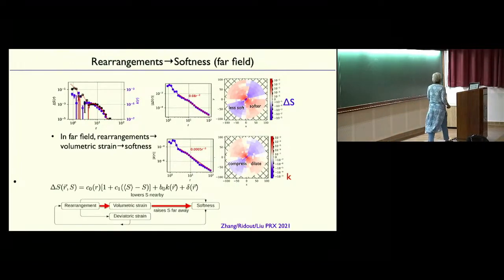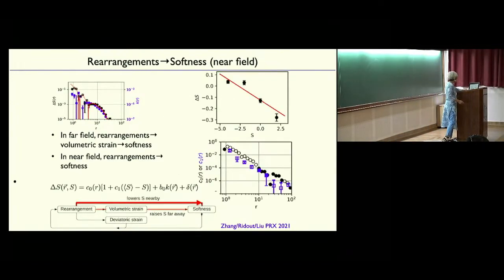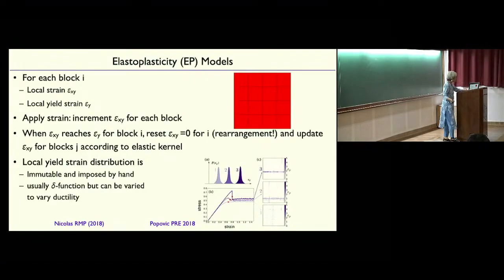That's the near field effect. And it turns out that the near field effect has a different form. You can subtract off the far field effect and look at what's left. And what you see is that the near field effect has this simple form where I have a coefficient that decays with distance, okay? And then there's something that wants to drag softness to its average value. So what happens nearby, you change the softness, but in a way that wants to restore it to its average value. So it has this sort of form, okay? And then there's Gaussian noise. Okay, so that just emerges from the calculations.